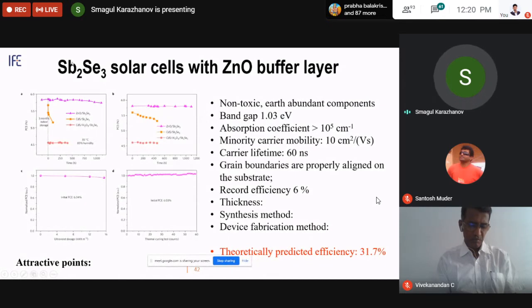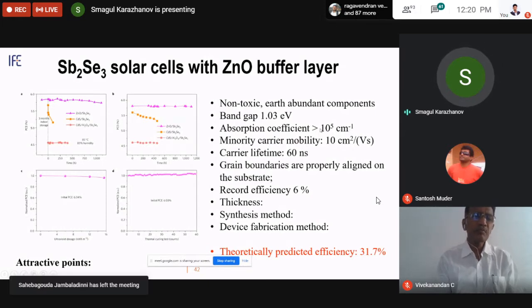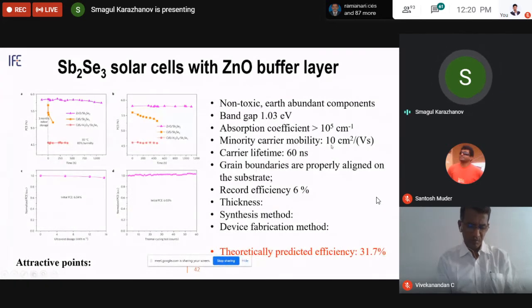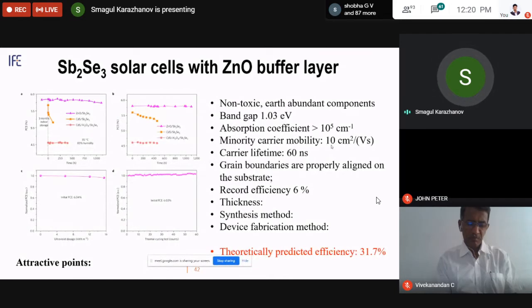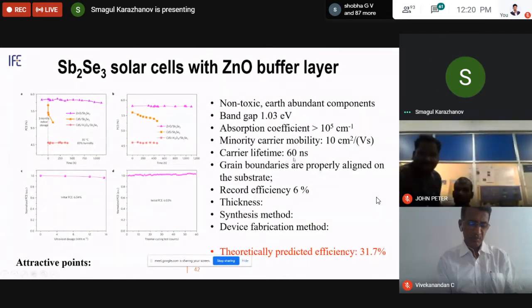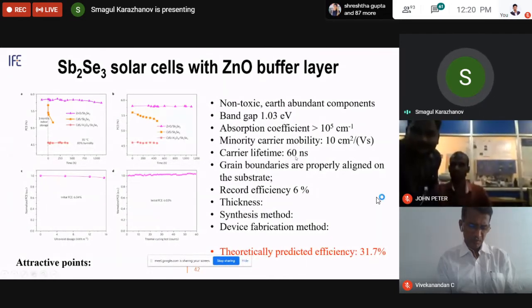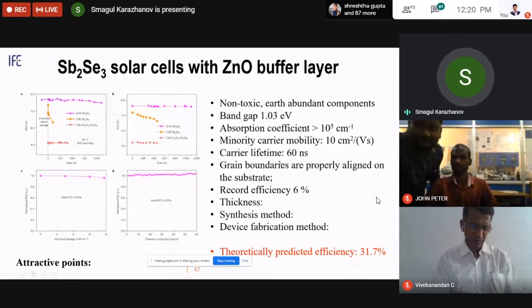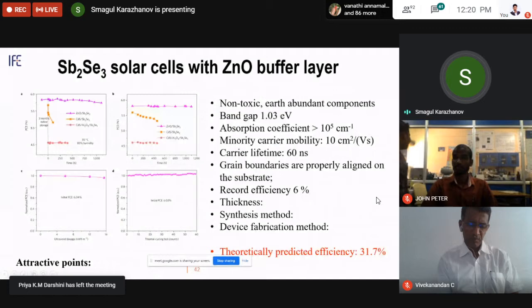The band gap of antimony selenide is about 1 electron volt. It possesses a very high absorption coefficient, and the minority charge carrier mobility is of course too small. It's about 10 cm² per volt second. Charge carrier lifetime is too small, and one should be able to control grain size. And the theoretically predicted efficiency is around 32%, which is high.